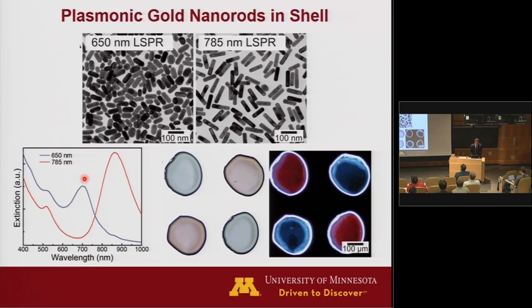So the shorter rods here have a peak around 700 or so. The longer rods around 880. And you can see that where this one rod is a peak, the other rod is a valley. And so where the first rod is a peak, the other rod is a valley. So in principle, if you can pick your laser wavelength to hit right here at the maximum, it should only trigger heating of one type of rod and should not trigger at all the heating of the other type of rod. It should be an orthogonal system. Does that make sense?